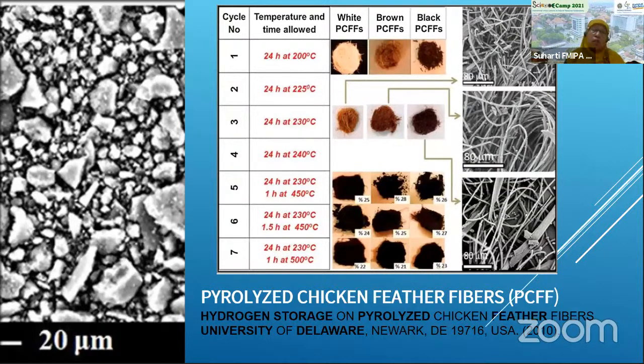Normally they use carbon dioxide, which is very cheap. Nitrogen is also relatively cheap. And you see here, they have seven cycles to change the feather into material which can absorb hydrogen. The first is 24 hours at 200 centigrade, and then it increases a little bit like this, but free of oxygen. When oxygen is introduced into the system, the process is damaged and cannot be continued, becoming carbon. Because all will burn into gas, nitrogen oxide, carbon dioxide, and so on.